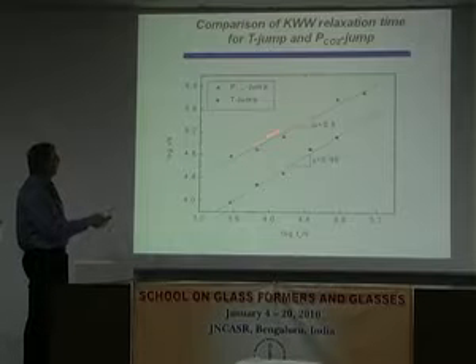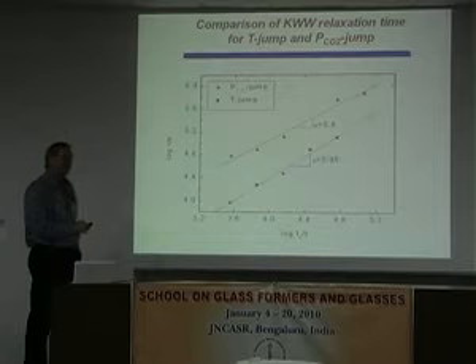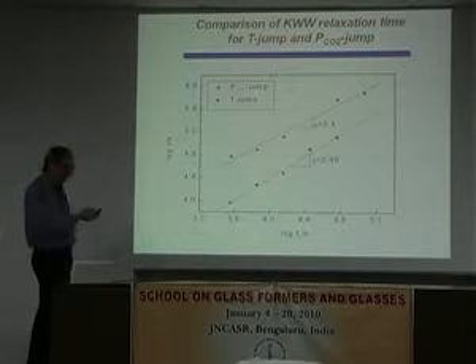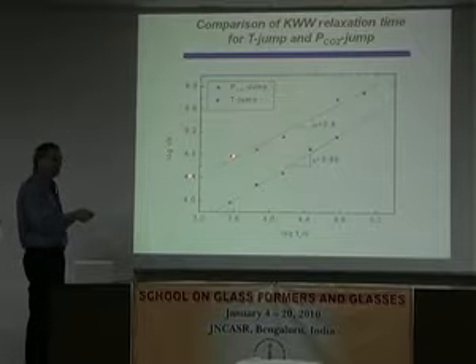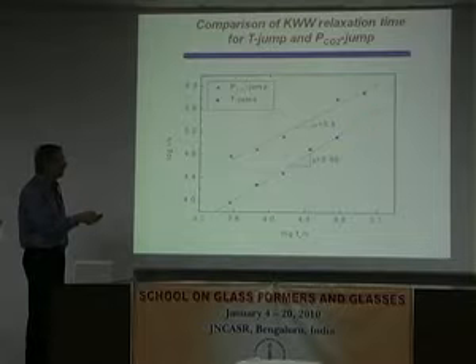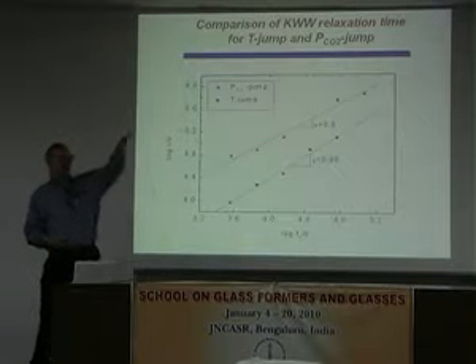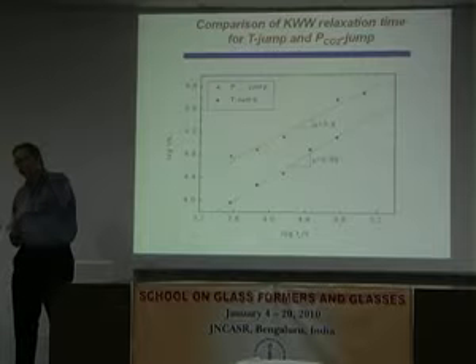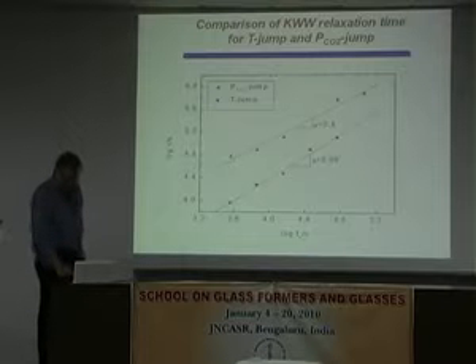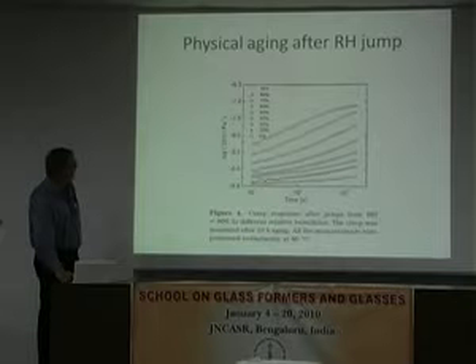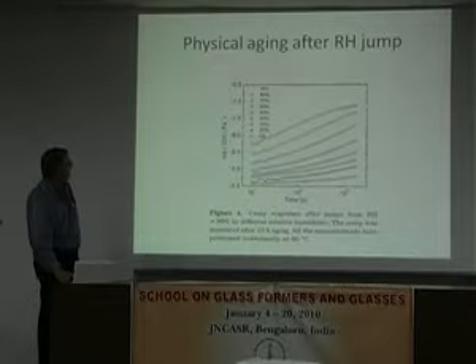But it's still very surprising that the carbon dioxide jump, which we know has a higher volume after we do it, we know at least that much, is still relaxing more slowly and evolving at a different rate. Okay? And this was similar to what we saw with the relative humidity jumps, where the structure, even though it had a higher free volume, if you like, was relaxing more slowly than the temperature jump experiment. So these are the behaviors after relative humidity jumps.